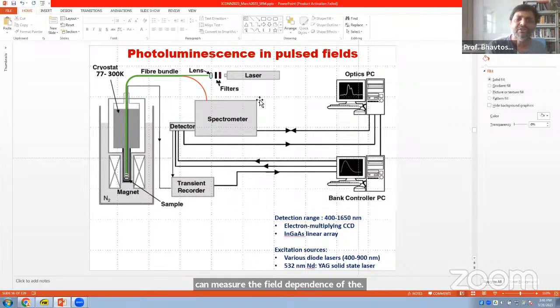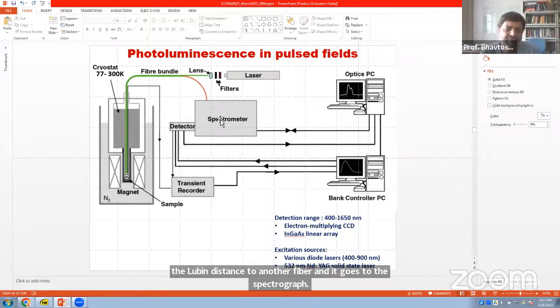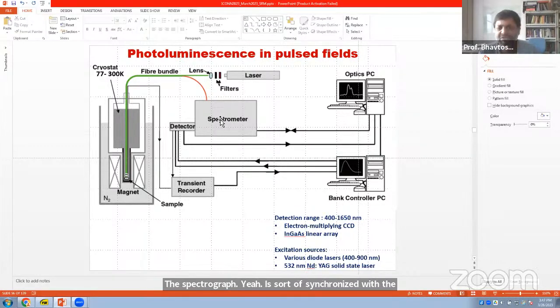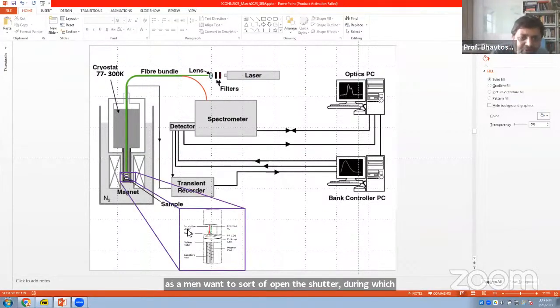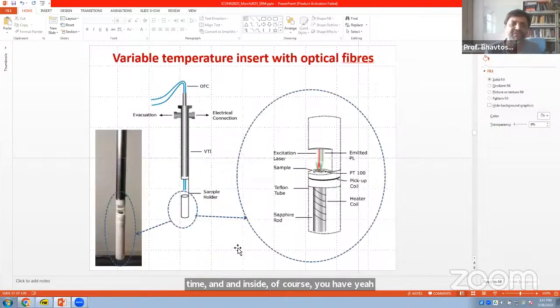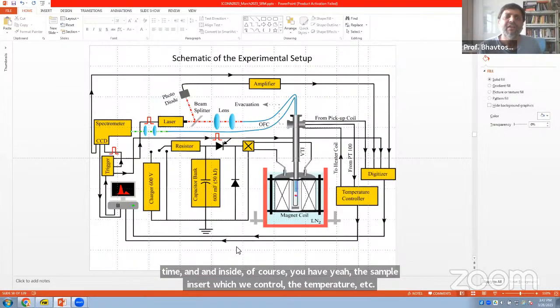That was one part, and then of course you have to make a cryostat. We have two cryostats, one which is a homemade closed cycle cryostat, which can go down to around 9 or 10 Kelvin base temperature. The other is just a simple liquid nitrogen cryostat. Here you have a laser which excites the sample through a fiber optic cable, and then you collect the luminescence through another fiber which goes to the spectrograph. The spectrograph is synchronized with the field pulse, so that you can do synchronous measurements, opening the shutter at the right time. And inside, of course, you have the sample insert where you can control the temperature, etc. So this is what the setup looks like.